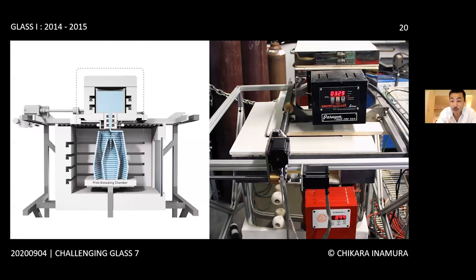The system is composed of three thermal zones that are independently thermally controlled to melt the glass nuggets and retain molten glass, to regulate its flow, and to remove the thermal stress through the annealing of printed glass. The upper assembly of the melter and the nozzle moves in X and Y directions, and the print bed moves in Z direction inside a heated chamber.